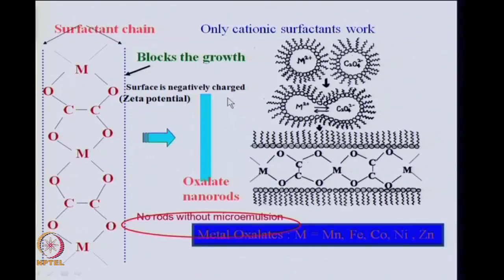And we find that in our microscopic studies, and we can explain why metal oxalate nanostructures form this kind of linear chains. These oxygen ions, which are negatively charged, will attract the polar head group, which is positive in case of CTAB, the cationic surfactant. So, the cationic surfactant will be aligned along these surfaces, and hence growth will be more amenable along this axis, but not along this axis. This is one of the mechanisms that has been proposed for the formation of anisotropic nanostructures in metal carboxylates, especially when you take cationic surfactants.